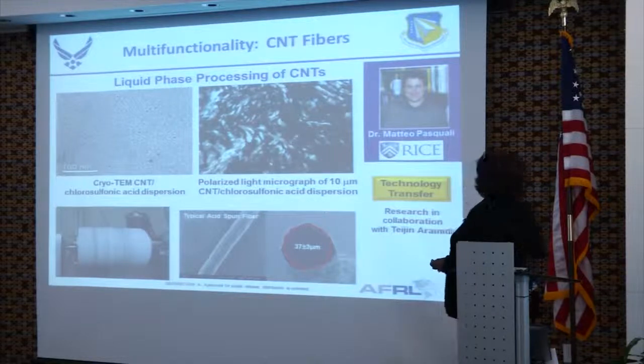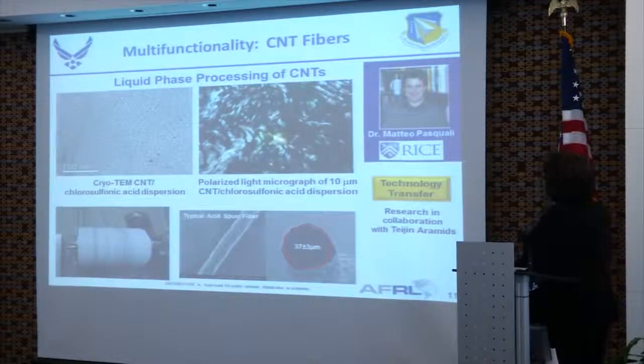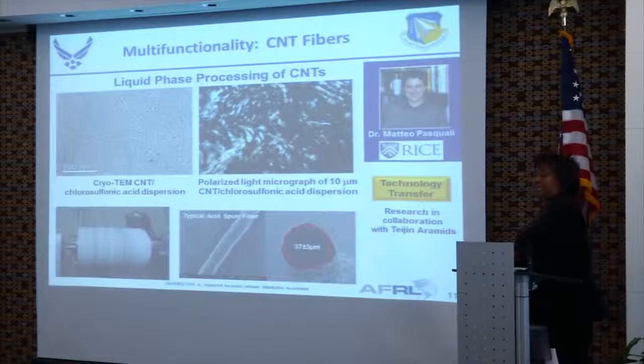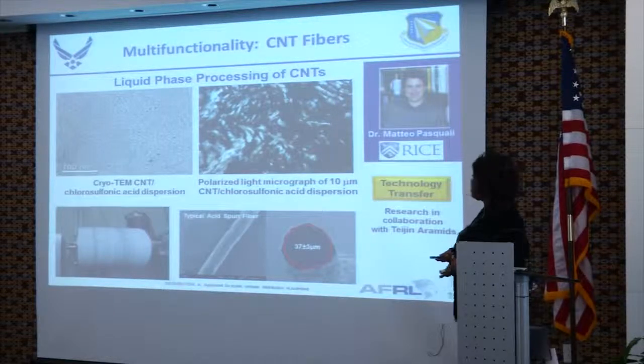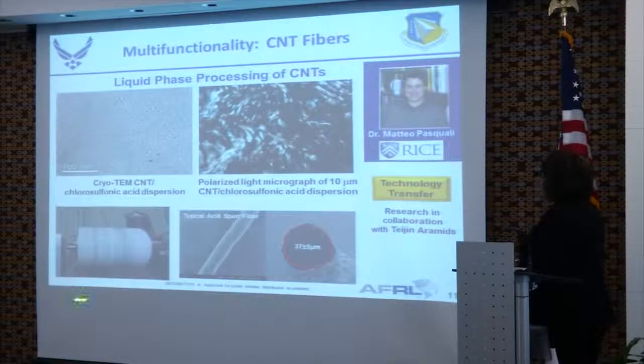And so this indicates that these materials might be spinnable and actually made into fibers, and that's what he has done. He's worked to spin these, and these are really the first carbon nanotube fibers that have been made. You see, these are not nanofibers like the work of in the first project. These are micron size fibers.